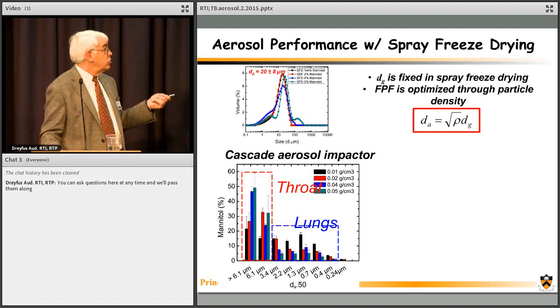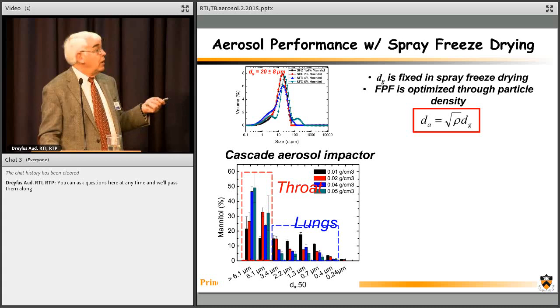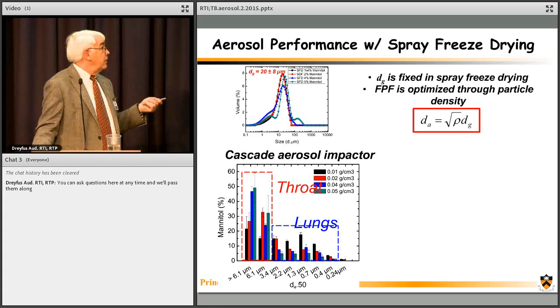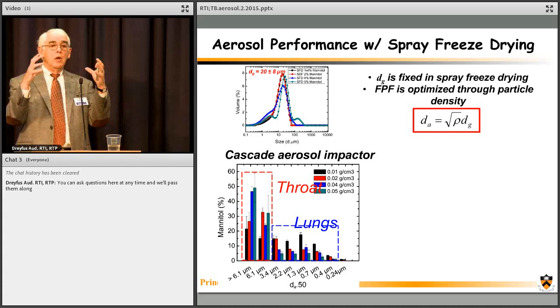So the larger particles would be captured in the throat, and what you want is the smaller particles captured in the lungs. You go to the literature, Dave Edwards and others, and the prediction is that the aerodynamic size of particles goes with the square root of density times the geometric size. And the argument is that if I have a great big low density material, it will follow the airstream and inertially not be captured.